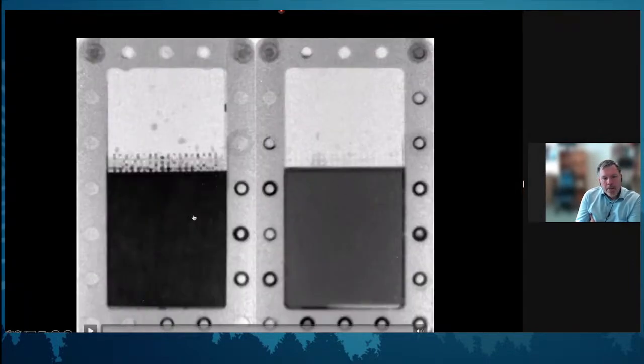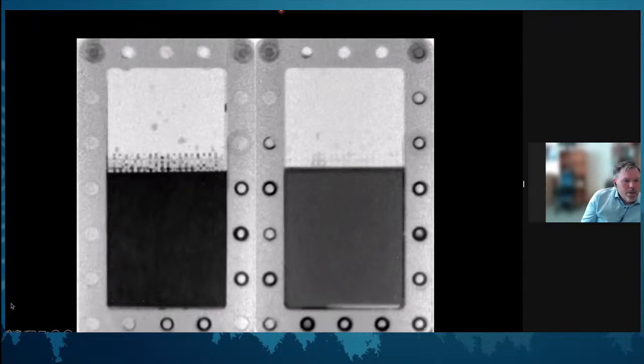So the total amount of water plus the cellulose mat to the left is double than it is to the right. And since neutrons are absorbed by the hydrogen, that means that less is passing through. So black means that there is more water present. We can also see the aluminum a little bit, but the good thing about using neutrons is that the aluminum is an excellent window. It's a good material that doesn't take up so many neutrons, so it works as a window if you're doing any type of other visual experiment.